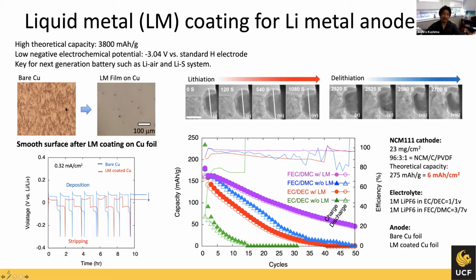And because of the liquid nature of this coating, even if you put the lithium on, once you take the lithium out, this liquid coating transitions from solid to liquid and back and forth. So it's some kind of self-healing coating that will enhance the lithium materials. And by using this coating, you can significantly enhance the cycle lifetime of the lithium.